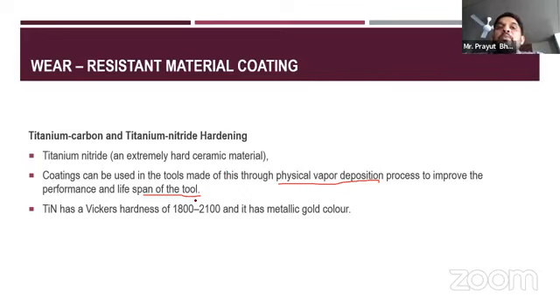So it is majorly used in tools. And the Vickers hardness for this is mentioned as about 1800 to 2100, because it's a very hard material, and you cannot measure it in HRC, you cannot measure it with the BHN tool. So it's very hard. And again, we do the coating of it because it's a very costly process, and it looks like a metallic gold color. So when you see a certain tool and it's this color, there might be a possibility it has been coated with titanium nitride.